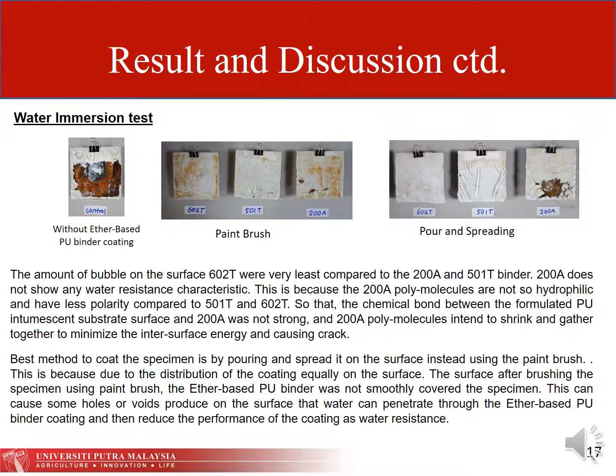In the water immersion test, the amount of bubbles on the surface of 602T was very least compared to the others. 200A does not show any water resistant characteristic. This is because the polymolecules are not so hydrophilic and have less polarity, so the chemical bond between the formulated PU intumescent substrate surface and 200A was not strong, and the polymolecules tend to shrink and gather together to minimize the interfacial energy, causing cracks. The best method to coat the specimen is by pouring and spreading it on the surface instead of using a paintbrush. This is because the coating is not distributed equally on the surface, which can cause some holes or voids on the surface that water can penetrate through the ether-based PU binder coating, and then reduce the performance of the coating as water resistance.